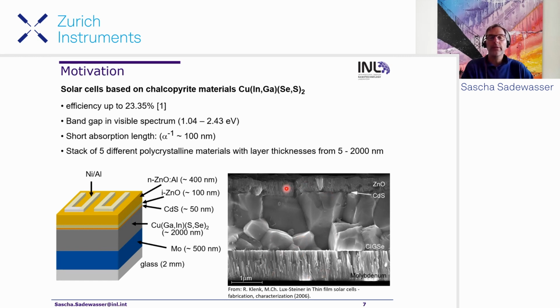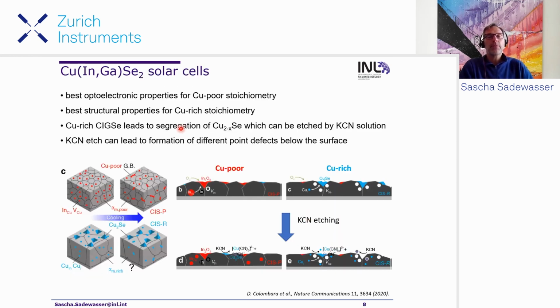Then we have a moly back contact, a buffer layer, a transparent conductive oxide window layer. So mostly we are looking in our experiments at this absorber layer, so we don't have any of the top layers on top. And of course, with the grain size of 1 micrometer, these materials are ideally suited to study them by scanning probe microscopy. So in this study, we looked at the difference between materials that are grown in copper poor and copper rich ways. When you look at these materials, the best optoelectronic properties are actually found for copper poor stoichiometry, whereas the best structural properties are found for copper rich stoichiometry.